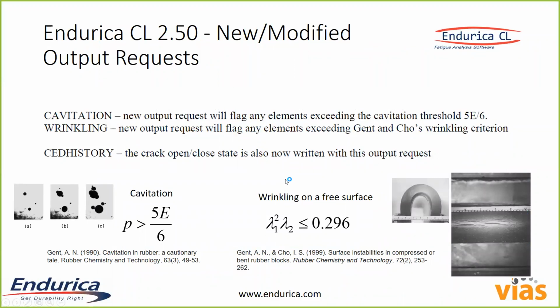Another feature that's new with Endurica CL is we have outputs that allow you to ask for cavitation, wrinkling, and crack open close state information. So with cavitation, sometimes in rubber, depending on your loads, you can actually have failures that are not necessarily due to fatigue. For example, if you put a high hydrostatic tension on the rubber, where the hydrostatic pressure gets bigger than 5/6 of the Young's modulus, voids will spontaneously open up in the rubber, and that can be a failure mode. Endurica knows how to check for this, and if you ask for it, it'll give you a time history of where and when cavitation might be happening.